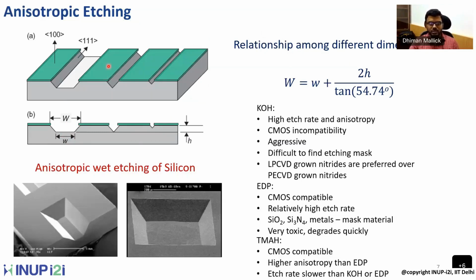If you want to do anisotropic etching, there are a few popular anisotropic etchants of silicon. Starting with potassium hydroxide, this has a very high etch rate and is anisotropic, but it is also very aggressive in nature, which is why its etch rate is also high. But the problem is that it is sometimes very difficult to find a proper etching mask for this KOH agent. Only a material which is very uniform and without any kind of hole can be used as an etching mask for KOH. LPCVD grown nitride is a very good example of an etching mask for KOH etching, because these LPCVD grown nitrides are typically very uniform without any pinholes that allow the solution to go inside the mask layer.